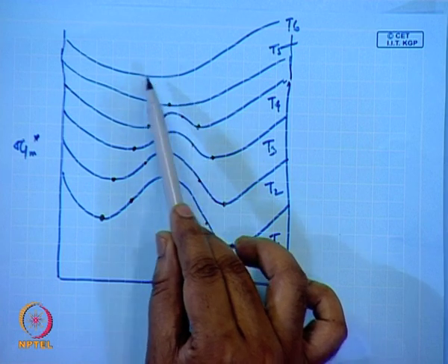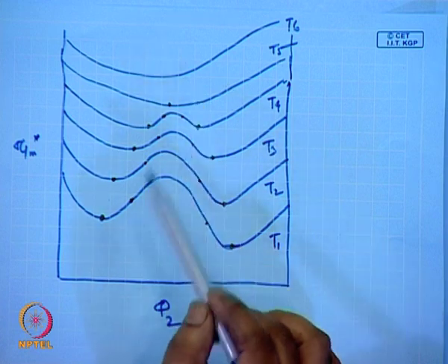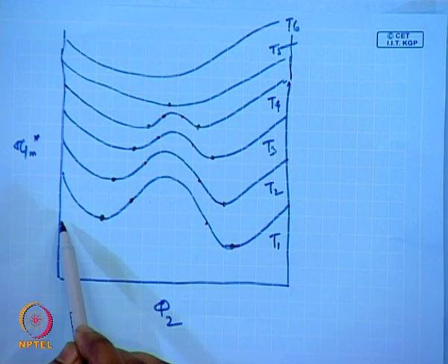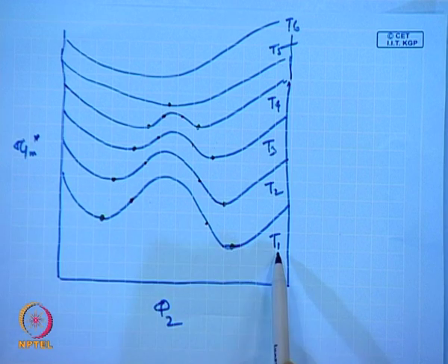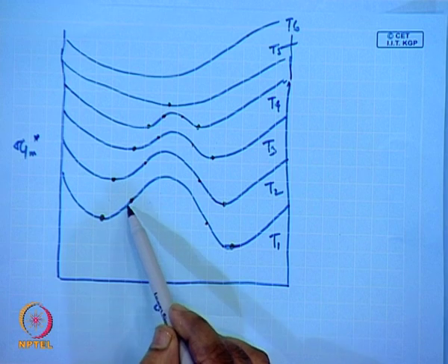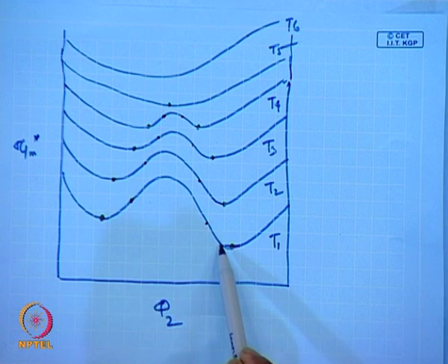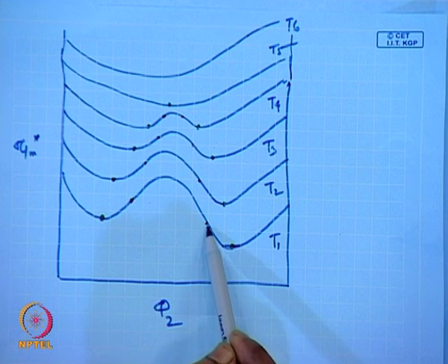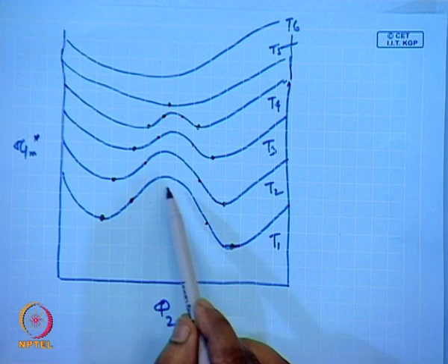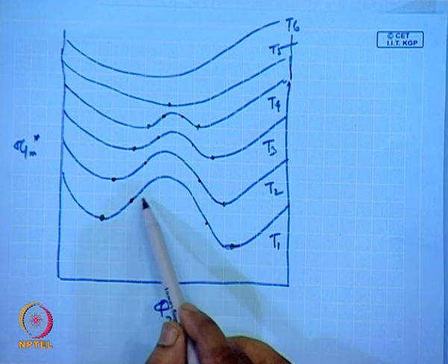These correspond to different temperatures, and we discussed that there could be one type where the polymer is soluble in the solvent at any composition, and then another type where you have complete solubility on the left hand side and on this side, and a region of metastability, thermodynamically unstable but metastable for small fluctuation in composition, and then you have a completely insoluble or unstable region.